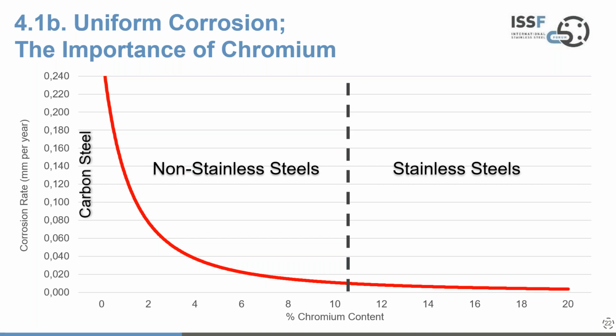And really, you can classify in the steel family three groups of materials. Carbon steels right on the left-hand edge, the non-stainless low alloy steels in the midsection, and then to the right of the vertical dotted line, stainless steels. And that's where you've got 10.5% chromium or more. And it's very easy to see the relationship. As you add chromium, and once you get above 10.5% chromium, the corrosion rate drops dramatically. And it's close to zero when you're in the higher end of the chromium range on this particular chart. So I think that's a very clear demonstration of how important chromium is.